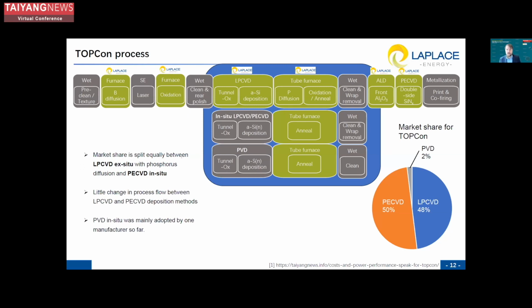We can also see that between LPCVD and PECVD, there's very little change in the process flow. On the LPCVD side, we do the deposition in the intrinsic state and then do an ex situ phosphorus diffusion before the anneal. In the PECVD, we have an in situ amorphous silicon deposition, which is then still followed by an anneal. Both of them have wraparound and therefore need a wraparound removal, while the PVD can live without this, but still needs to get to the wet chemistry afterwards for a clean.